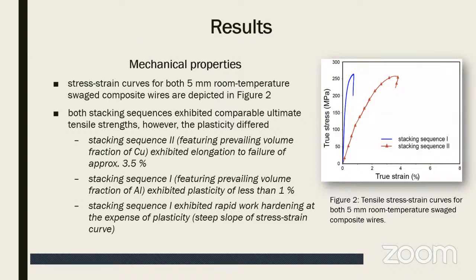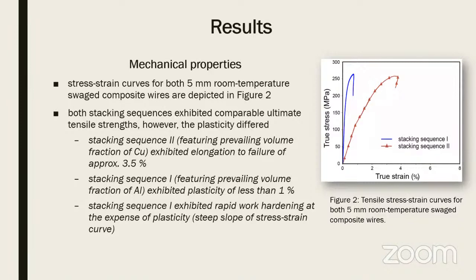The results of tensile testing are seen in figure 2, in which we have two tensile stress strain curves for both these stacking sequences. We see that the ultimate tensile strength was comparable for both the swaged composites. However, there were differences in their plasticity. For stacking sequence 1, the plasticity was very low, the elongation to failure was less than 1% of true strain. However, for the stacking sequence 2, it was more than 3%, approximately 3.5%.